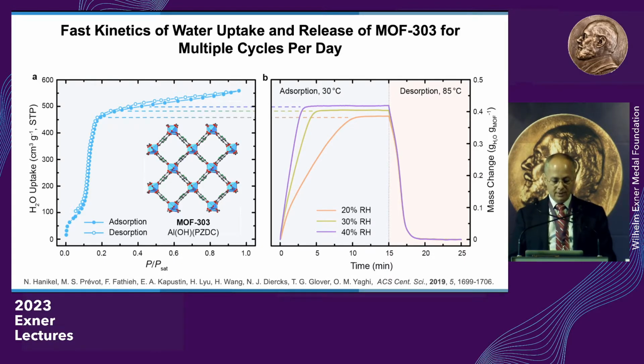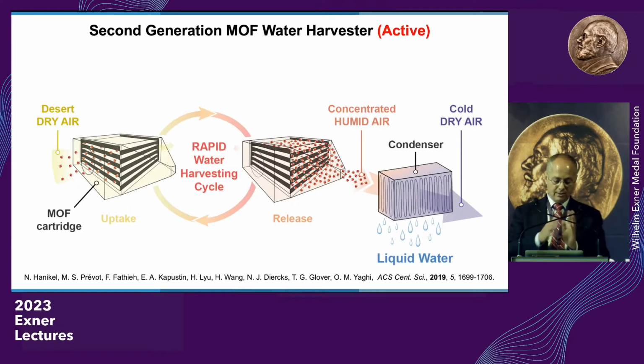Okay, so here filling up the pores is about 5 to 10 minutes, depending on the humidity. And taking it out of the pores, if you want to enhance the kinetics, you heat it up to 85 degrees, no big deal. And you can get it out within three minutes. So we designed another prototype. This one is more shelf-like to expose more of the MOF.